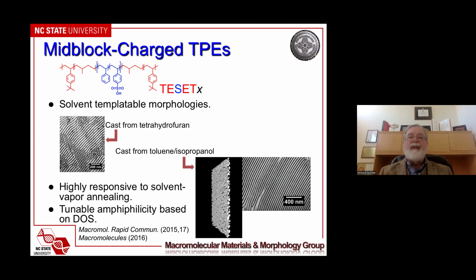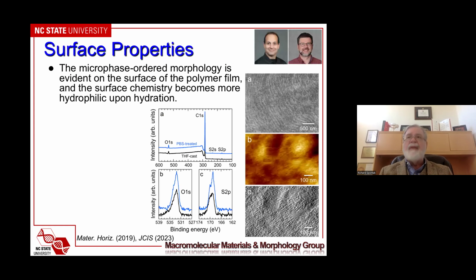Okay, now let's go ahead and see about the surfaces of these materials. Because if we're talking about antimicrobial properties, then we're talking about surfaces. So this is an ultra high resolution, low voltage SEM image showing that those lamellae extend to the surface. These are complementary AFM images where we have height and phase. You can again see those structural elements on the surface. In terms of the chemistry, if we subject the polymer to phosphate buffered saline solution, which is typically what we use for application of microbes, we see that we have an increase in the sulfur and oxygen peaks. So the sulfonic acid groups are at the surface.